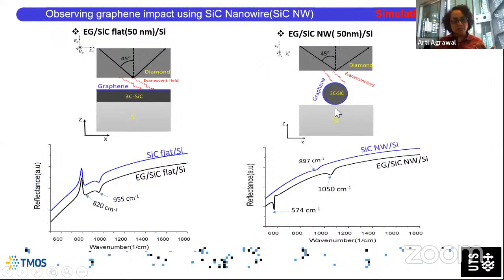But now, instead of being in a planar configuration, we have moved to creating a nanowire of silicon carbide and then coated it with graphene. If you compare these two graphs from left to right, you can see that the features have changed substantially. So clearly something special is going on with the nanowire. And this is what we will be exploring. But comparing the two nanowires, plain silicon carbide and the one coated with graphene, we find again their features are similar. They're not too different between each other.